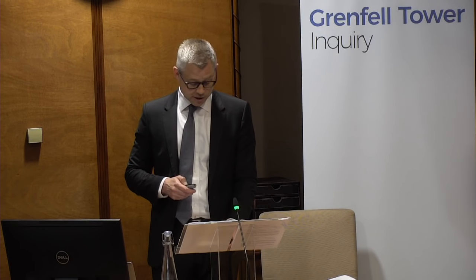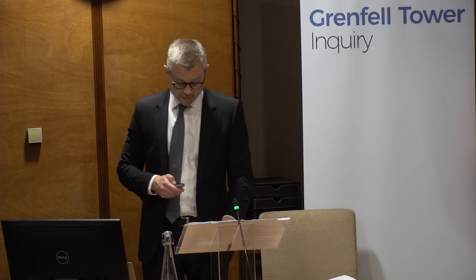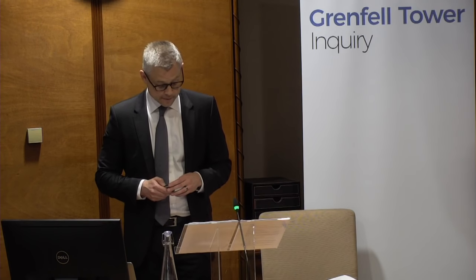Ignition, flammability, flame spread, and fire growth are all influenced by numerous factors, including material properties, chemical composition, orientation, geometry, and interactions with other materials. Upward flame spread on a solid fuel is rapid because the hot flame and gases preheat the material ahead of the burning zone. Downward and horizontal flame spread is generally slower because preheating of the fuel ahead of the flame front is greatly reduced. Almost all of these concepts are important in order to understand even my most basic matchstick demonstrations of some of the relevant flame spread mechanisms.